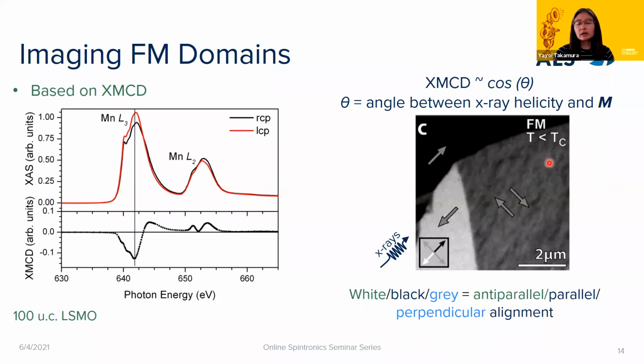So this is an example, for an unpatterned LSMO film, of what the typical domain structure looks like. The way we read this is we always need to know the direction of propagation of the X-rays. For this particular image, it's coming at an angle, right? Regions which are black and white are going to be parallel and anti-parallel to the X-rays, and regions which are gray are going to be perpendicular to the X-rays. It follows that cosine theta dependence, so you can have angles in the middle. But in this case, where we've got fourfold symmetry in the sample, we expect only these four domains. We can't tell the difference between these two domains, which are pointing up versus down, because the angle is still always 90 degrees to the X-rays. But that's how we can image and determine the local direction of the magnetization in these materials.